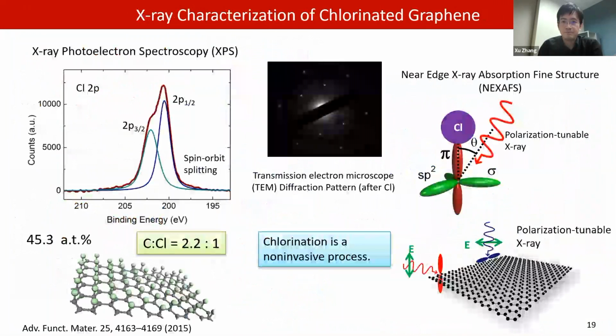In order to confirm this is a non-invasive process and understand the bonding nature behind this process, we also did X-ray spectroscopy to characterize the chlorinated graphene samples. First, from the XPS, we quantified the surface coverage of chlorine to be about 45%. Very surprisingly, such a large amount of coverage does not disturb graphene's intrinsic structures and properties. TEM diffraction pattern can also clearly reveal this. We also did a near-edge X-ray absorption fine structure spectroscopy, which allows tuning the polarization of X-ray beam and probing the fine structure of the surface states of chlorinated graphene.